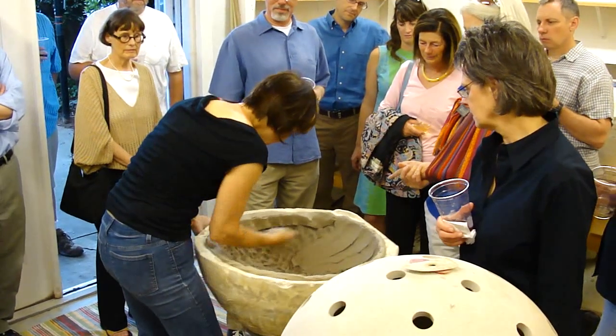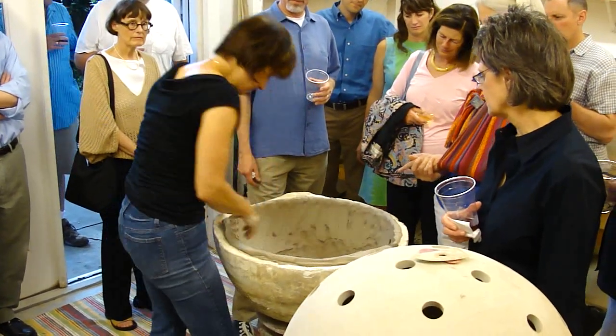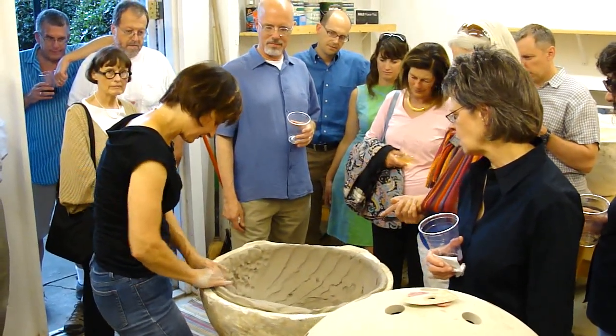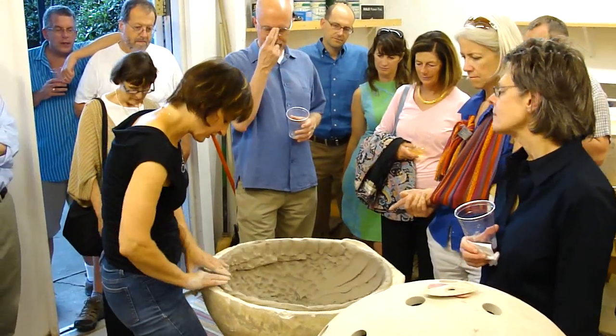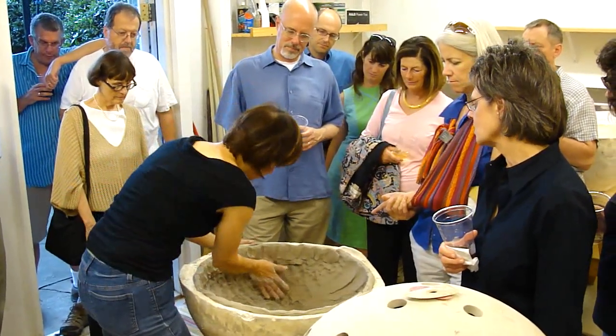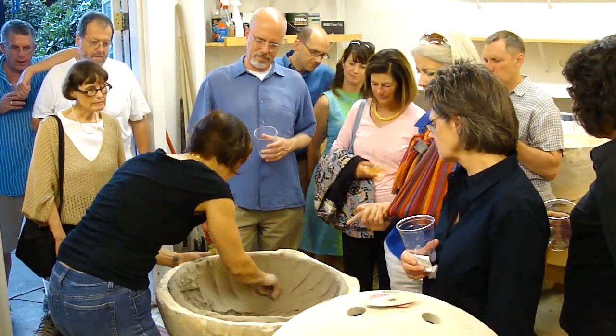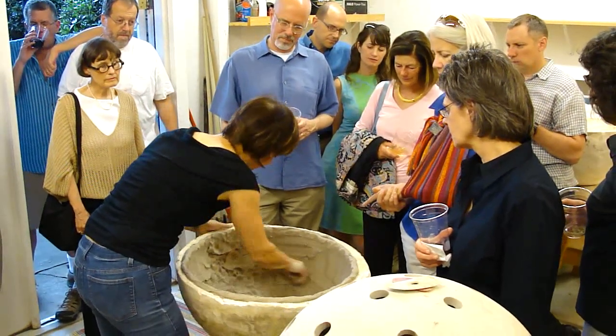Yeah, and like I said earlier, I work with a stoneware clay, which is called stoneware because it's stone-like. It's very, very tough. It has lots of fire clay in it. And what is fire clay? Fire clay is what's used for bricks that are going to be exposed to a lot of heat. It's a very coarse clay. It's not like your kaolins, like your porcelain or china, those kinds of things that are very fine, very small particles. Fire clay is a much coarser clay, a much stronger clay.